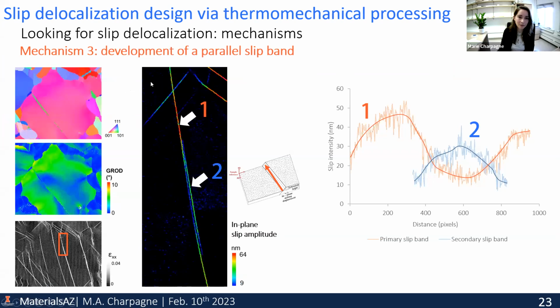Okay, third mechanism that I want to detail really quickly is the development of a parallel slip band. And this is illustrated in this pink grain here. We're looking at this region in particular, where we had the first slip band that formed early on during loading, and then the second one that formed parallel to it. And again, you see where the second slip band formed, so it has this intensity of slip. The first one actually decreased in intensity, which is a very interesting mechanism to distribute plastic deformation much better in this alloy.